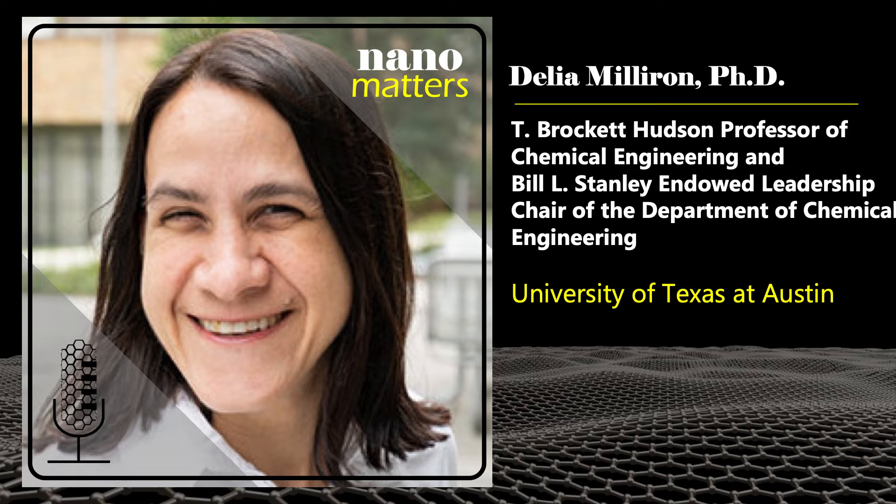If these are intended to be energy-saving devices, how much energy does it take to do the switching? It takes actually very little energy. We've collaborated with energy analysis engineers who can model the energy performance of buildings, and it's less than one percent of the energy savings required to do the switching — so it really becomes a negligible energy use. Just like a battery holds its charge until you use it, these windows, once set to a given optical state, don't consume any additional energy to stay in that state. Only when you're actively switching to a different mode does the window consume any energy at all.